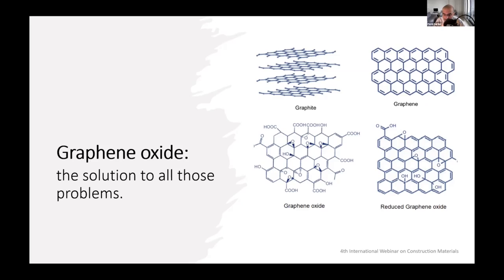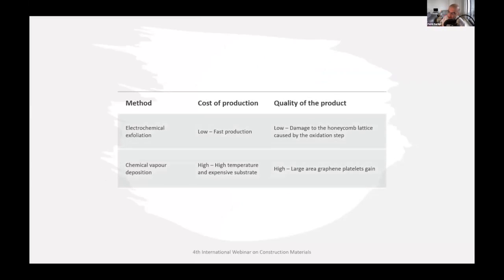Nevertheless, the major advantage of reinforcing concrete with graphene oxide and not graphene is the affordability of this material, because after reviewing the literature, there has been no significant difference observed between these two in terms of mechanical performance in concrete. So basically, by using graphene oxide instead of graphene, you can save a lot and get the same outcomes from the mechanical perspective. So there are two main methods of producing graphene particles, which I will explain in this